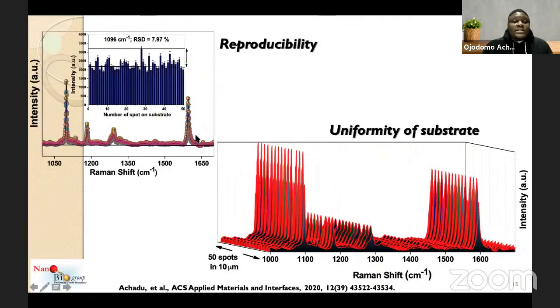So next, which is also important, was to test the reproducibility and uniformity of the substrates. This is quite important in SERS because one of the drawbacks of SERS technology is the issue with reproducibility, and therefore it makes it difficult. We were able to confirm a very good reproducibility of the whole system, the detection, and also the substrate in the first place, because we can have quite a repeatable and consistent measurement at different spots.